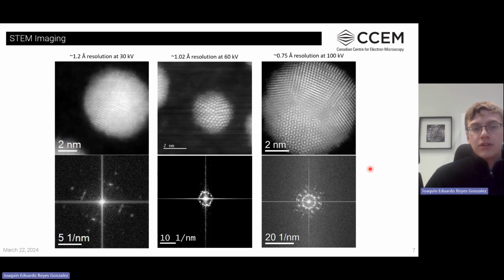At 60 kV, you can get about an angstrom, perhaps a little bit better, and you can still do some very nice imaging, some very good spectroscopy. And at 100 kV, you can get about 0.7, 0.75 angstrom spatial resolution. You could probably push these a little bit further if you do some slight further tweaking, but these are already very good. These are about what you would need to get if you were pushing, say, 200 kV on other systems, just because of how good the corrector is on this system.